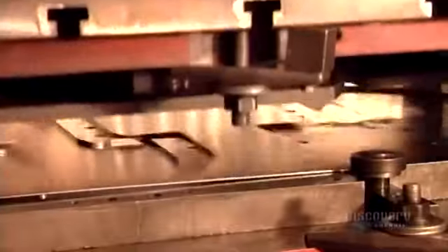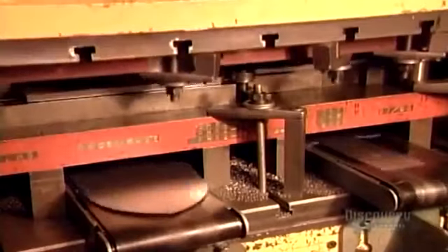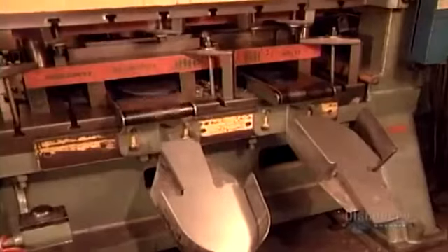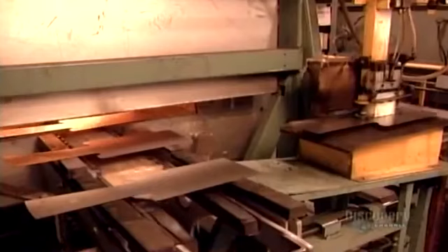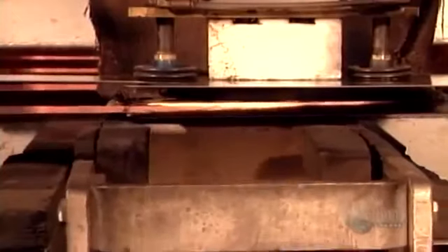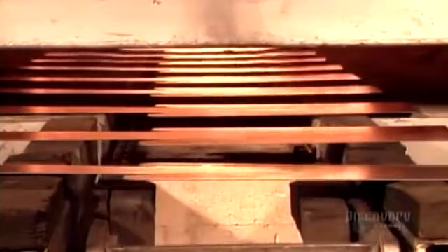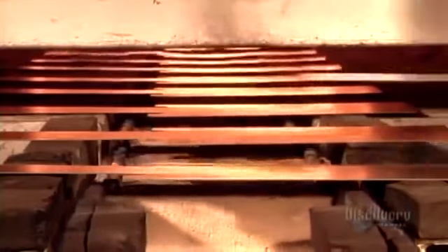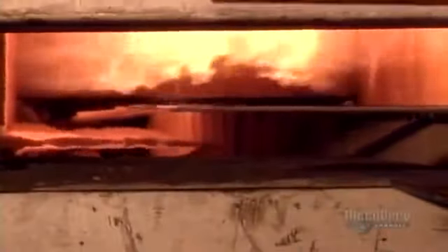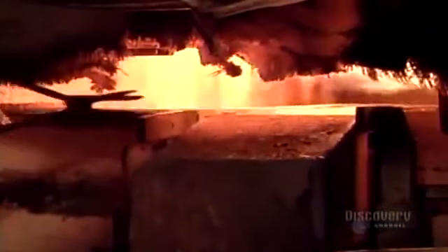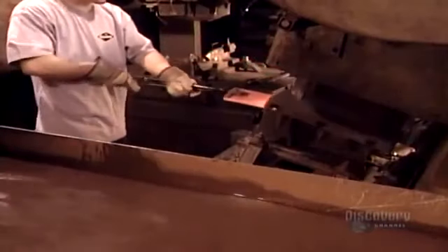Elsewhere in the factory, meanwhile, a heated forming machine stamps out the steel blanks that workers will shape into blades. A robotic arm loads the blanks into an oven. In a mere 4 minutes, the oven heats the steel to almost 1,000 degrees Celsius. This intense heat makes the metal malleable. Workers then take out and shape one blank at a time. They have just a few seconds to form the steel before it cools off.